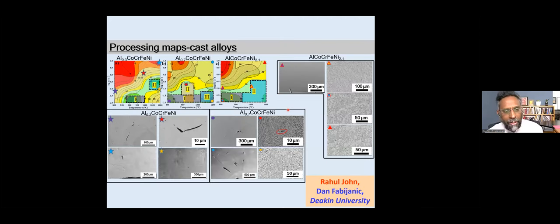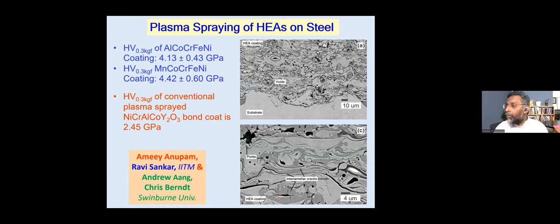And we also did what is called processing maps in these alloys. I do not want to go into detail because I was told I have only 30 minutes. So we started looking at how to use these materials for what kind of applications. One such application is coatings. Nickel-based superalloys are usually coated to improve their high temperature capability. And we tried to use these high entropy alloys as a coating material and compare with conventional coating materials. We find that the alloy that we have coated has about 4.4 gigapascal strength, whereas the conventional alloy has only 2.4 gigapascal strength, which tells you that you have much higher strength and wear resistance, so that they can be wonderful replacements to existing conventional alloys.